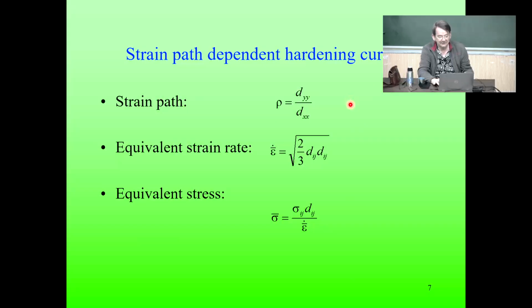Now, strain path dependent hardening was imposed here. This is the rho defining the strain path. Equivalent strain rate was the von Mises strain rate. The equivalent stress was not von Mises, as I explained to you before already. For an anisotropic material, you cannot use the von Mises equivalent stress formula. You have to use the so-called